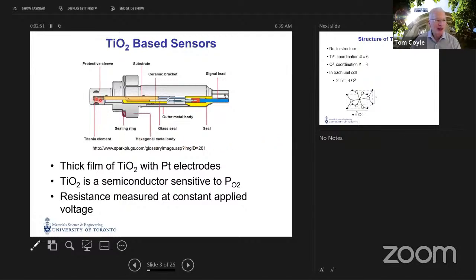And so the titanium dioxide element here at the tip can be a thick film coating or a thin sintered disc. It turns out that titanium dioxide acts as a semiconductor, and that semiconducting behavior is sensitive to the amount of oxygen present in the atmosphere. And therefore, by monitoring the resistance of this titanium dioxide element, we can monitor the oxygen partial pressure. So how does that work? And to answer that question, I'm going to have to make a pretty big circle before I get back to explaining exactly how that works.